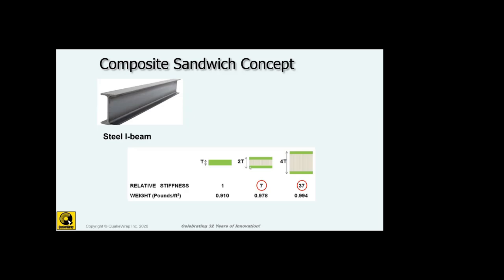So what we do is we separate those 2 carbon layers by putting a core material in between. And you see that if you enlarge it by double the size, you get 7 times the rigidity. Or if you put a little bit thicker core in there and make it 4 times the thickness, you get 37 times the rigidity. So you really get a lot for your investment.